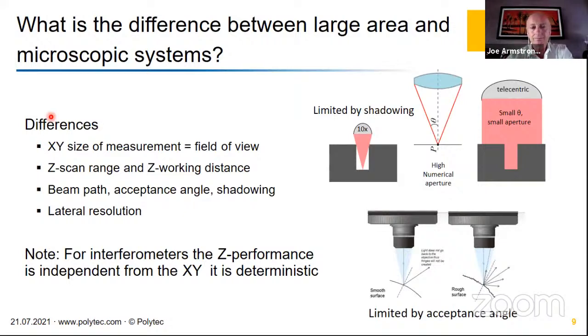There are some other differences, and these are really enablers to how well you can measure a surface. So it's like the strategic approach. If we consider a microscope type system, then you have a higher magnification, you have a higher XY sampling rate. But as you can see, your lens is typically much closer to an object. You have to turn the light much faster. So if you start to look at recessed surfaces, you start to get maybe a bit of shadowing. Whereas differences with the telecentric lens, you have a larger field of view. The consequence of that is a lower XY sampling rate, but you get very good penetration into a surface. So you have a different XYZ capability.